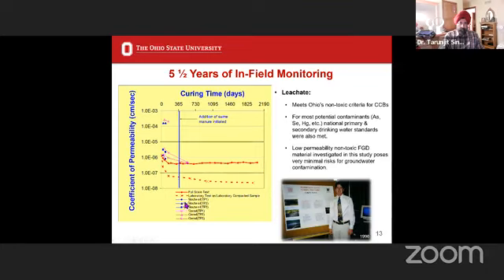We then looked at Boutwell tests and at some core samples, and our research has shown that they are not reliable. Boutwell tests are very difficult to do, and core samples, as you know, can have a significant amount of disturbance along the edges. What was interesting was the lab test. These were samples that we made in the lab, kept, and tested up to about 5 years.